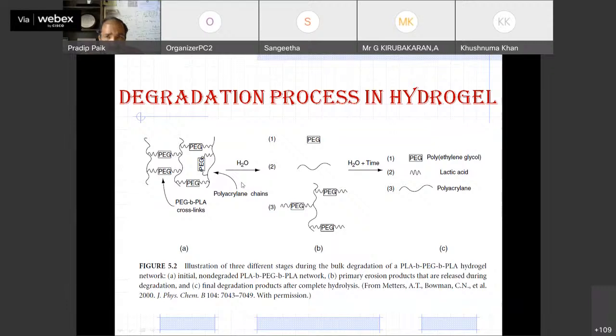Another thing is the hydrogel; let's say one example I have given, made up of polyethylene glycol, polylactic acid, polyacrylate. This type of hydrogel network will be there, and they can easily degrade in water. If they degrade, they again form polyethylene glycol, lactic acid, polyacrylic acid. Polyethylene glycol is very much biocompatible, and lactic acid, if it gathers inside the muscle, causes a lot of muscle pain. But whatever lactic acid they produce takes part in the carboxylic acid cycle inside the biological system, and it is useful.